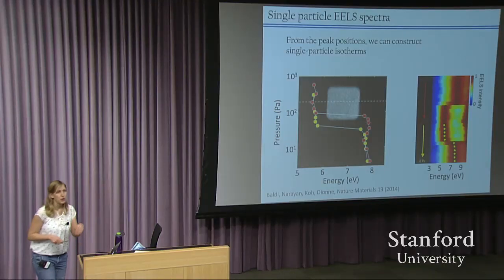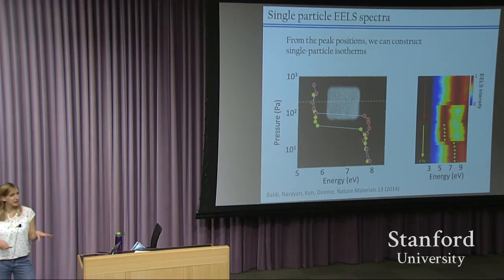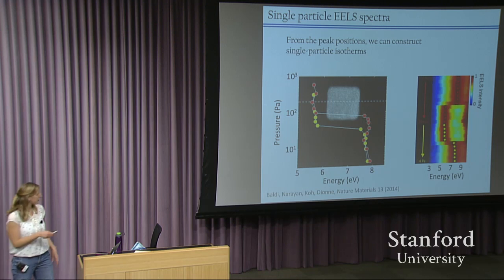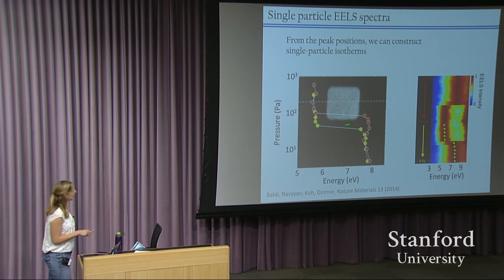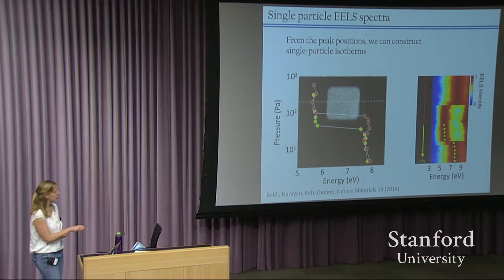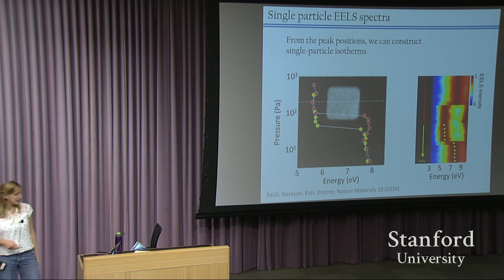You'll also notice that each of these isotherms is actually quite sharp. So it's unlike some of the single particle measurements that were out there and unlike the ensemble measurements that were out there. And also you'll notice that unlike bulk, there are no points that occur in this coexistence region. So you'll remember in bulk we had a phase diagram where in here we had both alpha and beta coexisting, but here when we're doing measurements in thermodynamic equilibrium, we don't see coexistence in these small nanoparticles.